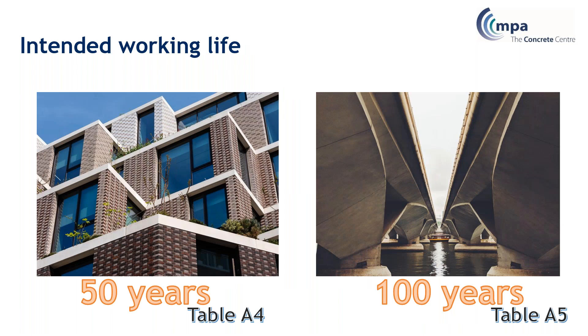Also within BS 8500 is the intended working life. There are two standard intended working lives: 50 years, which is really for buildings, and 100 years for civil engineering and monumental structures. If a client wants 60 years, the internal concrete at XC1 exposure is the same whether it's 50 or 100 years - no worries there. For external concrete, you can either treat 60 years as close to 50 and use Table A4, or do an interpolation between the 50-year and 100-year tables.